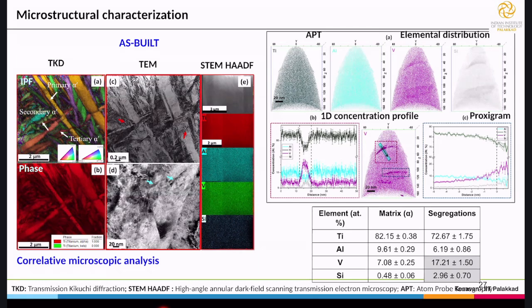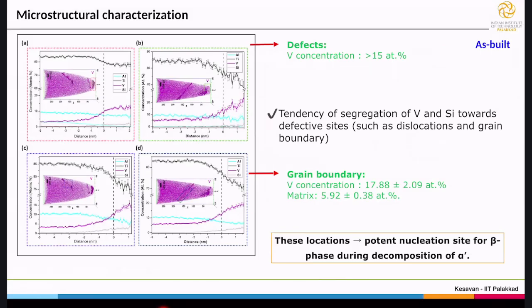Now, how do the segregated elements appear upon heat treatment? Very important: wherever there is segregation, there is a tendency for defect formation. There is a tendency of segregation of vanadium and silicon towards the defective sites, which means those regions will have a large amount of dislocations and grain boundaries, because they are all defects. So wherever there is such segregation, defects will be concentrated. These locations will act as potential nucleation sites for the beta phase during the decomposition.